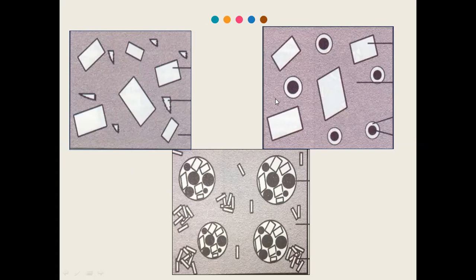The gamma 1 matrix is common to all. Only the addition is gamma 2, and that too in low copper, because it forms in that reaction. In high copper, in both admixed and unicomposition, there is elimination of the gamma 2 phase, so there is no gamma 2 phase at all in the matrix. So the matrix of low copper is formed by gamma 1 and gamma 2, while in admixed and in unicomposition the matrix is formed by the gamma 1 phase only.